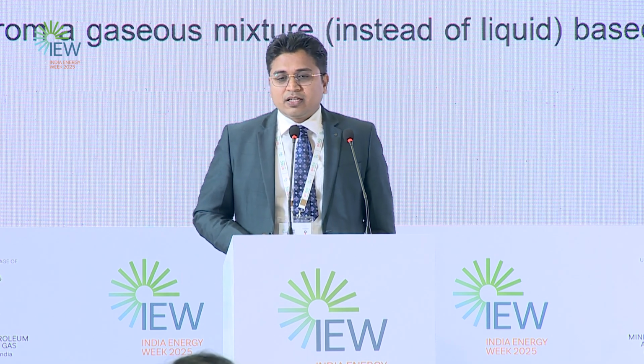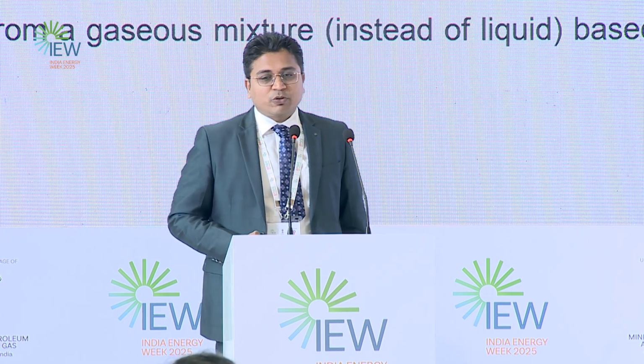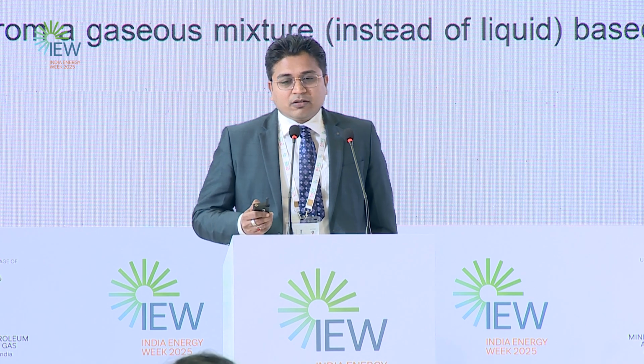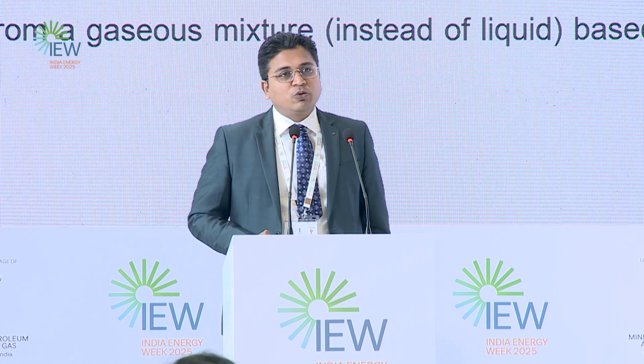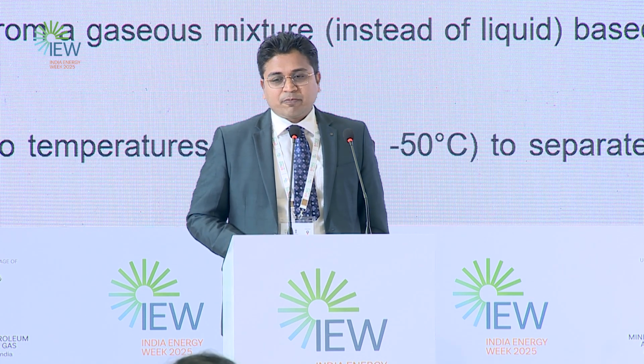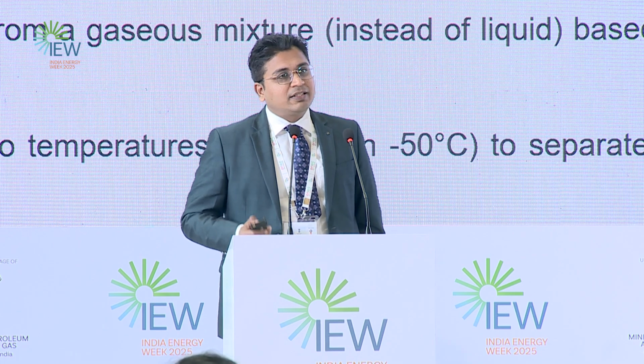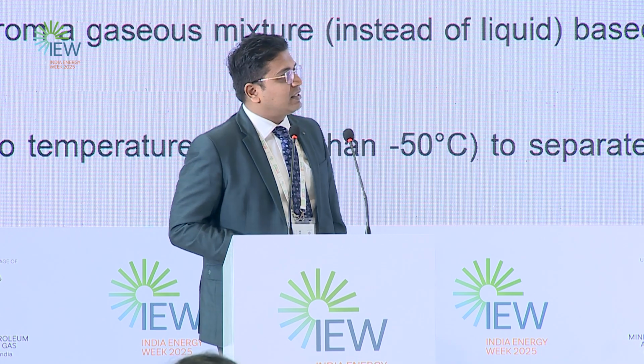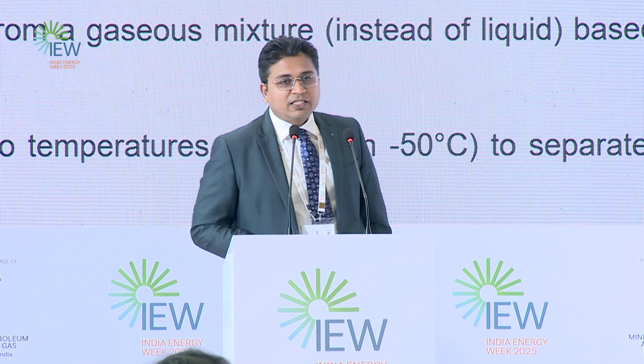The one which is very economical when we want to capture a large quantity of CO2, more than 1500 or 2000 tons per day, and which is the most commercial and economically viable technology, is cryogenic separation. It is similar to the distillation process, where the separation of CO2 is based on the boiling point range. The only difference is that the distillation takes place at sub-zero temperature, lower than minus 50 degrees Celsius.